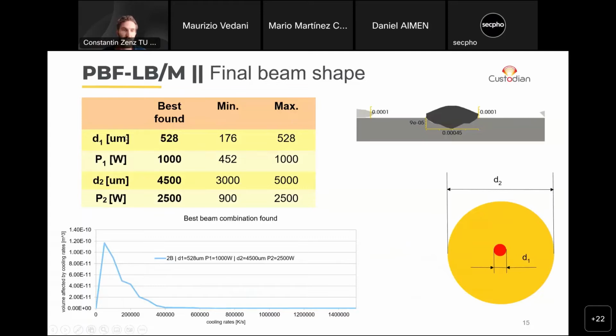In this way, we found a frame of optimum parameters, so minimum and maximum values for the primary and secondary beam diameter and power. This is especially interesting when we then look at dynamic capabilities of the MPLC, which range should be covered by the MPLC, and also the best found combination, which is actually quite a large primary beam. Of course, the larger the primary beam gets, the lower the cooling rates will be. But we also have to consider that we want to retain some precision in the machining capabilities. And also, the larger the primary beam becomes, the more power we need to penetrate the substrate, and then we are left with less power for the secondary beam.